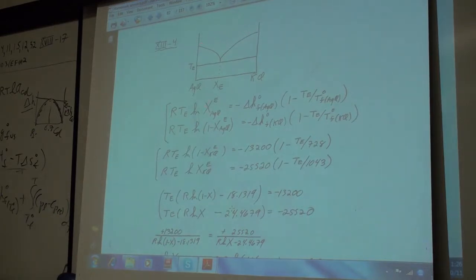In other words, an ideal liquid. I'm assuming the activity in the solid is 1, so the RT log activity in the solid term goes to 0. And this applies everywhere, so when the mole fraction of silver is equal to X eutectic, the temperature is T eutectic. So there's one equation from this point, and then on the other side you have the equation of the other liquidus, which is just replacing activity and mole fraction of silver by the activity and mole fraction of KCl, which is 1 minus X silver. So you have 2 equations, 2 unknowns, X and T, and you can solve.